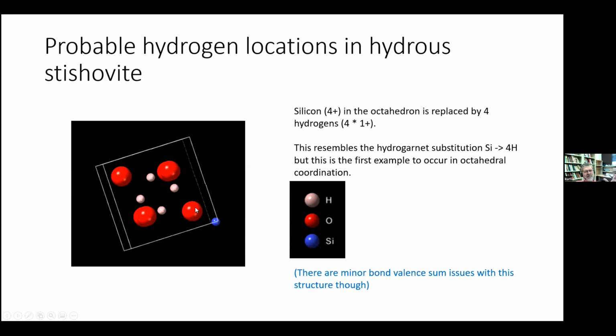And hydrogarnet substitution is substitution on a tetrahedron in garnet. This is hydrogen substitution on octahedron, but it's 4 hydrogens. So they have to bond to 4 of the oxygens. And here we put them on the bridging, on the edge sharing oxygens. They haven't been located, but we've done calculations. Dan Shim has done calculations. We've done a lot of work on this since then.